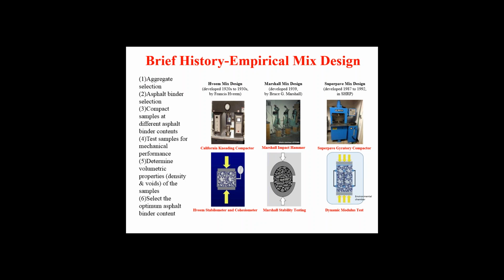One is forming the shapes, or forming a sample specimen. Another is evaluating some of the mechanical properties, like stability or strength of this material. Using this example, Superpave mix design consists of a few steps: aggregate selection, asphalt binder selection, compacting samples at different asphalt binder contents, testing the samples for mechanical performance, and determining volumetrics.